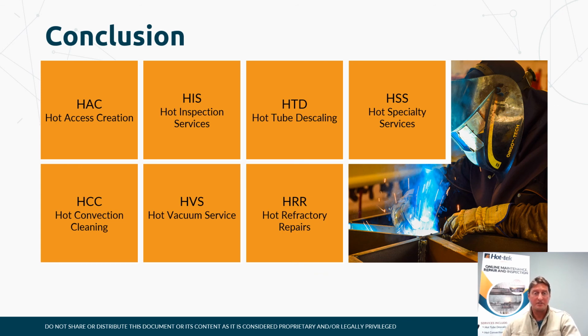The hot vac services, removing the fouling on our catalyst screens, and on the SCR, and hot refractory repair, which is again pretty much every applicable fired heater that has refractory that can fail, being able to fix that and at depth, and whether it be a ceramic fiber failure or a castable failure.